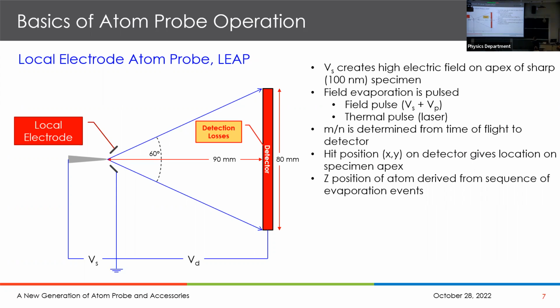as illustrated here, this might be the specimen. It typically is a conical shape. So there's a cone angle associated with that I'll get to in the next slide. But this is a counter electrode. And if you apply something like 10 kilovolts between the specimen and this counter electrode, you can create a very high electric field, which is high enough, and it's trying to pull positive charge out of that surface. So what actually happens is an atom on the surface, one of the valence electrons will tunnel into the specimen, and then that positive ion gets accelerated away. So it is a tunneling process.